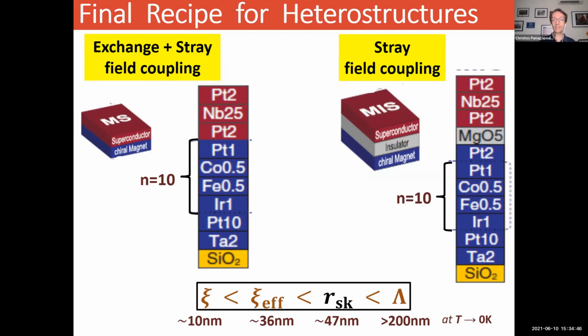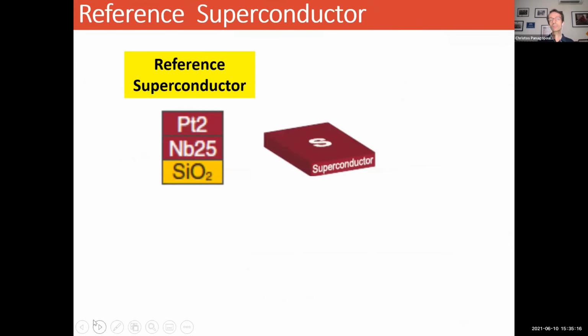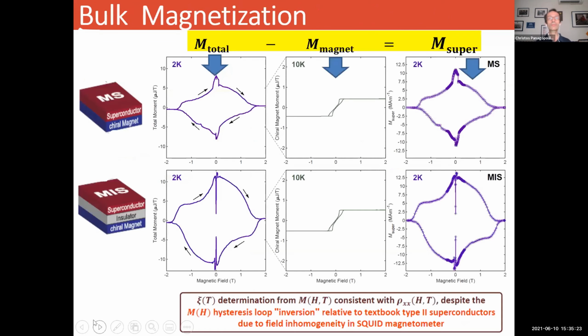And by measuring the coherence length, the Pearl length, and the skyrmion radius directly with our imaging techniques, we know that our skyrmion radius is 47 nanometers, and it is between the effective coherence length and the Pearl length, precisely as we want it based on theoretical estimates in order to have coupling between vortices and skyrmions. And for reference, we have our standard niobium film with the 2 nanometer platinum on top, our superconductor. So the first measurement to do is a bulk magnetization in order to see whether indeed the skyrmions are affecting the magnetic vortices and vice versa.